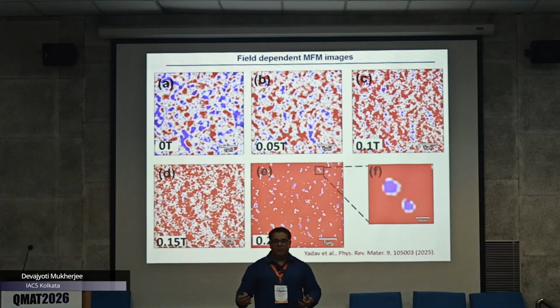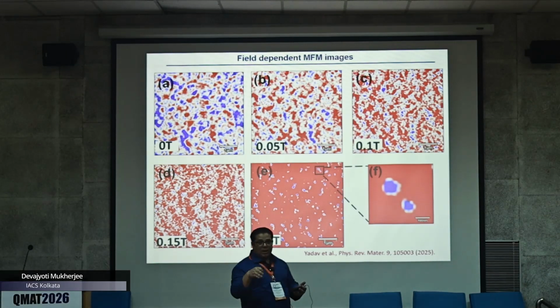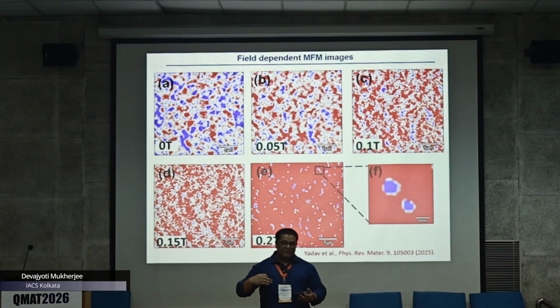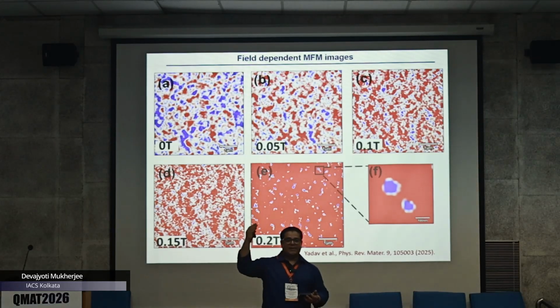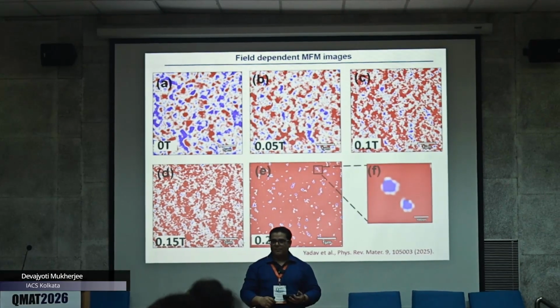So it's very difficult to correlate such localized changes into global effects. What we believe is that it's not just the skyrmions that are coming into the picture, it is the Rashba spin orbit coupling which is changing the anomalous Hall conductivity. So that Rashba spin orbit coupling is also an important part. We can always discuss. Yeah.